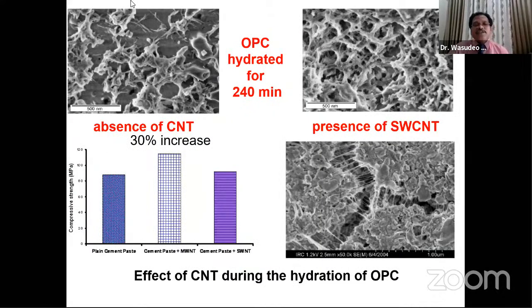Another application: we have also observed the effect of CNT on the hydration of cement. As we know, in this graph plain cement is taken, and the compressive strength of this material is shown here. When the cement is mixed with the single wall, the strength slightly increases, but when we mix with the multi-wall carbon nanotube, then there is a 30% increase in the strength of this cement.